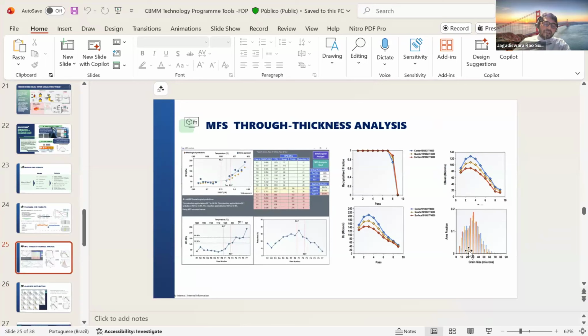So these are some outputs of the microsim I mentioned here, which is the mean flow stress relation with respect to each pass, from roughing mill stage number 1 to roughing mill number 6, as well as the different finishing stages. We compare the mechanical flow stress with the metallurgical flow stress. The blue lines indicate the mechanical flow stress, and the yellow dots indicate the metallurgical flow stress. It also gives information about the critical grain size and the recrystallization fraction at each pass, as well as the mean grain size at each pass, as well as the fraction.